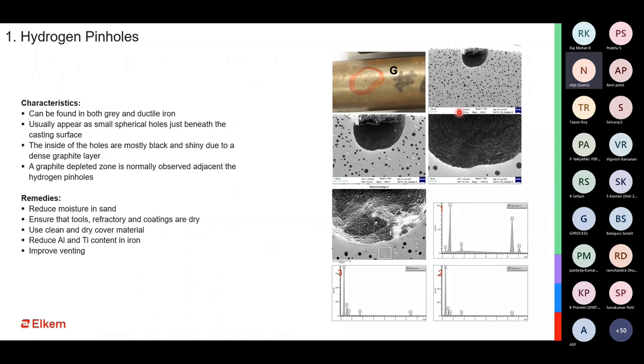Again, the resolution is quite similar to gray iron because the cause is similar. We have to reduce the moisture present either in the sand, the refractory or the coatings. We have to reduce aluminum and titanium, which increase the possibility of a hydrogen pinhole. Of course, we have to give sufficient way out for these gases, and therefore we need to improve the venting or the vent arrangements in the casting.